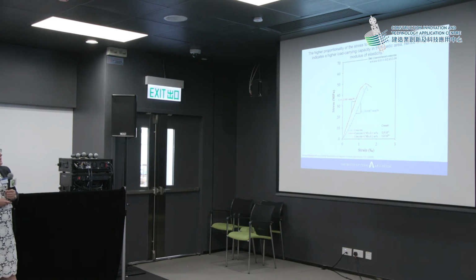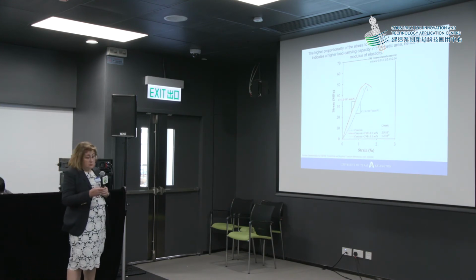So with QNM, quantitative nanoscale mechanical characterization, and by designing a simple experiment, you can see here the images from the atomic force microscopy. Here is the aggregate. We were able to identify the interfacial transition zone here and measure the modulus of elasticity, which is in absolute agreement with the results that we see at the macro scale. So back to the fact that we can increase the modulus, but we do not increase the compressive strength.